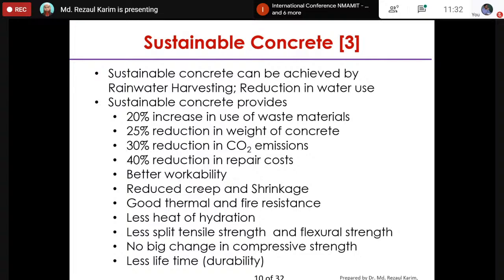These are also some information from the literature. Sustainable concrete can be achieved by rainwater harvesting and reduction in water use. Sustainable concrete also provides a 20% increase in use of waste materials, 25% reduction in weight of concrete, 30% reduction in carbon dioxide emission, 40% reduction in repair costs, better workability, reduced creep and shrinkage, good thermal and fire resistance, less heat of hydration, and less split tensile strength and flexural strength. In fact, there are no big changes, only slight changes in compressive strength.